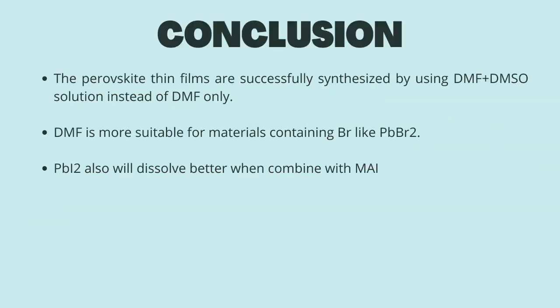As a conclusion, the perovskite thin films are successfully synthesized by using DMF plus DMSO solution instead of DMF only. DMF is more suitable for materials containing Br, like lead bromide. Lead iodide also will dissolve better when combined with MAI.